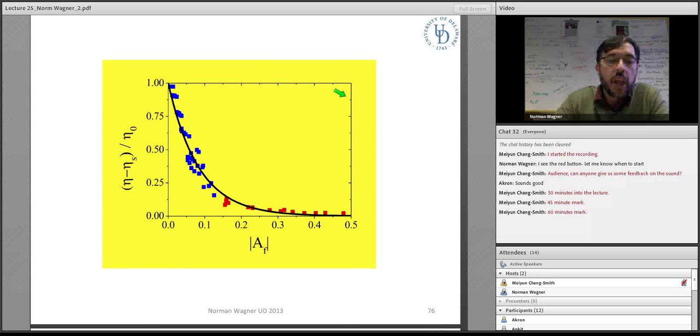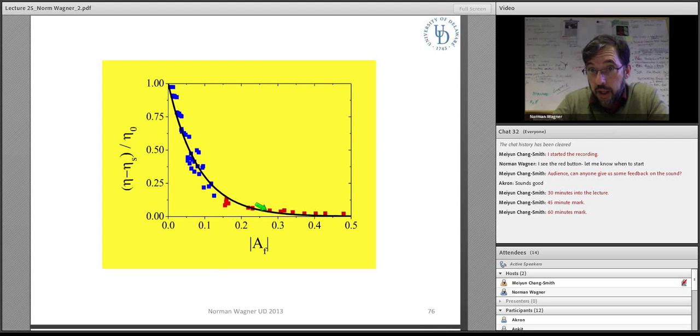Okay. And if I combine that information, I could plot the viscosity, if you will, due to polymer orientation as a function not of shear rate, but of the degree of alignment. And again, the blue points are in the isotropic phase, the red points are in the highly aligned state, and the line is the Giesekus model, rheology model for the fluid. And what it says is that this is just a continuous behavior, okay? We have two different types of states, but they're the same material. And they correspond to the same underlying structure of the material.